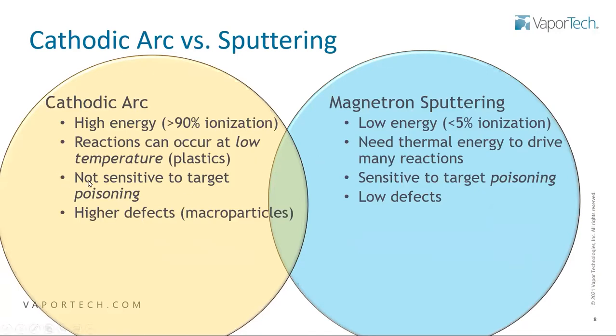Another thing is target poisoning, which is essentially a surface effect that happens on your target, whereby it reacts with the surrounding gases like the oxygen or nitrogen. Cathodic arc is less sensitive. Magnetron sputtering is quite a bit more sensitive. So this is a lot easier to control the environment in which the coatings grow and react.